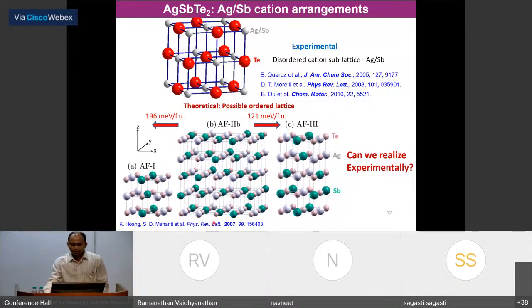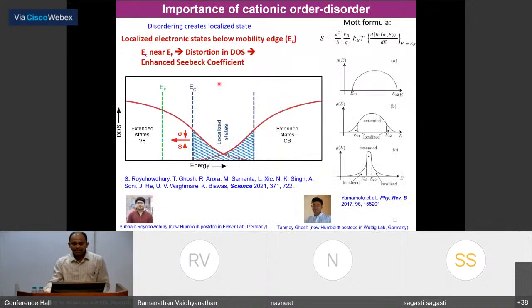But the paper from the Mahanti group at Michigan State, a PRL paper in 2007, predicted that this compound can be stabilized in an ordered form, where silver and antimony are ordered. We have been looking for this ordered structure since 2012 in this class of compound, but we could not find it experimentally. You can ask me, why are we looking for this ordered structure? The reason is that disordering can tune the electronic transport very heavily. It has an independent control on electronic transport, such as electrical conductivity and Seebeck coefficient.